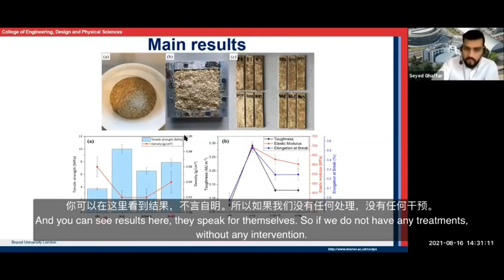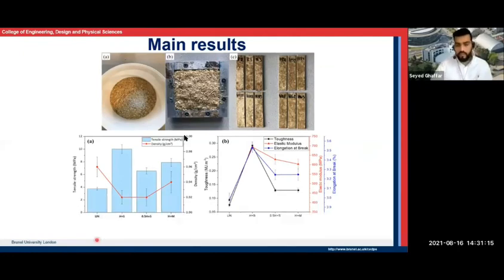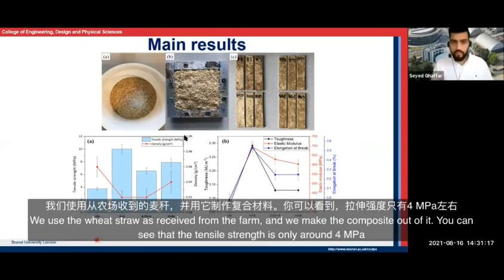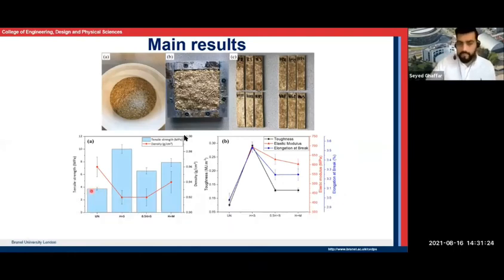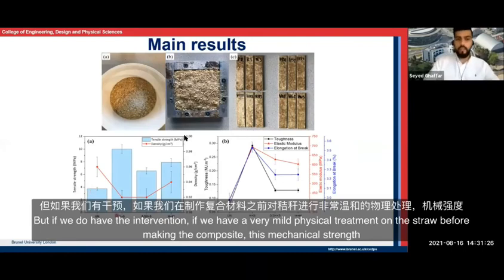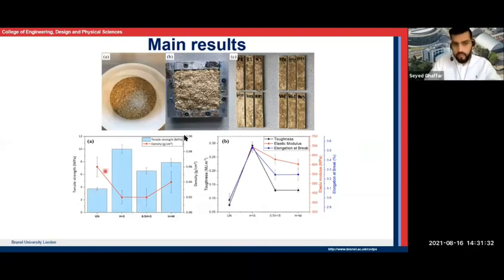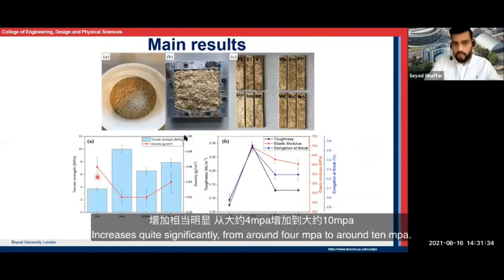They speak for themselves. If we do not have any treatment, without any intervention, we use the wheat straw as received from the farm, and we make the composite out of it. You can see that the tensile strength is only around 4 megapascals. But if we have a very mild physical treatment on the straw before making the composite, this mechanical strength increases quite significantly from around 4 MPa to around 10 MPa.